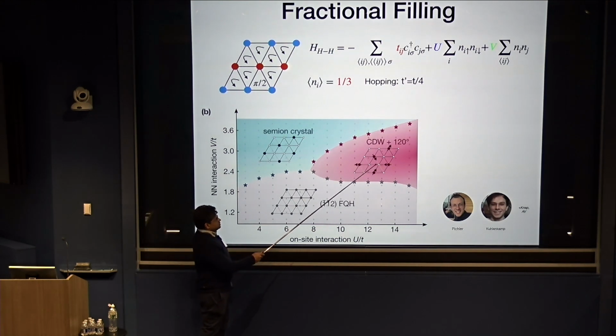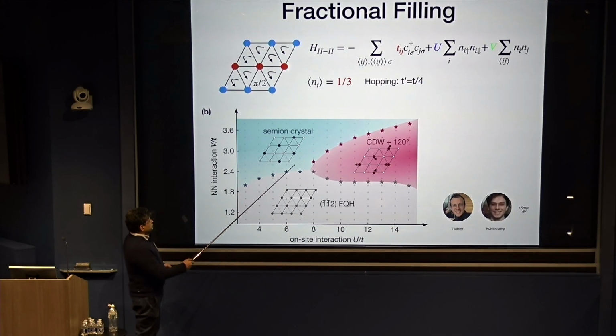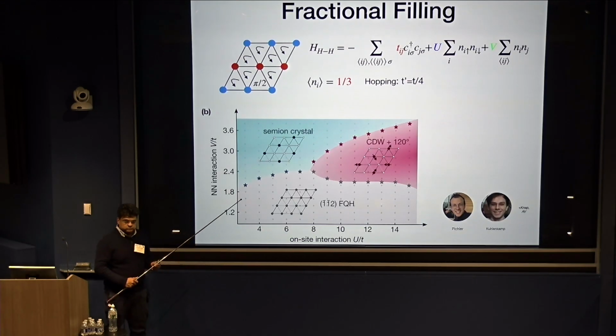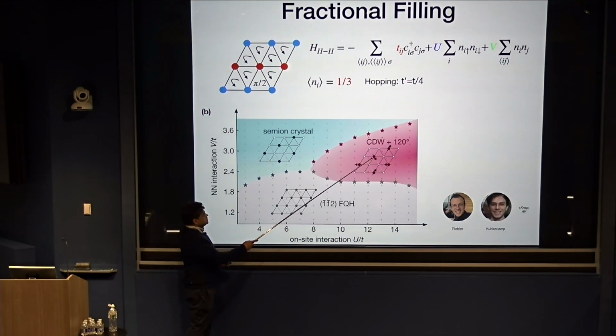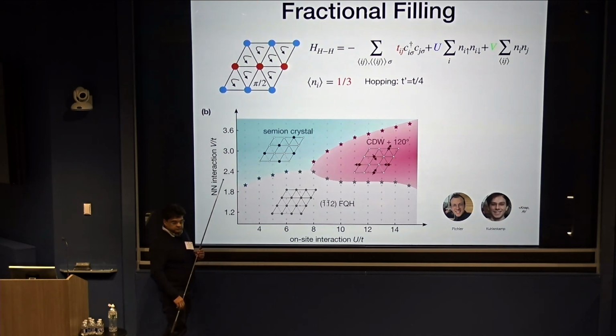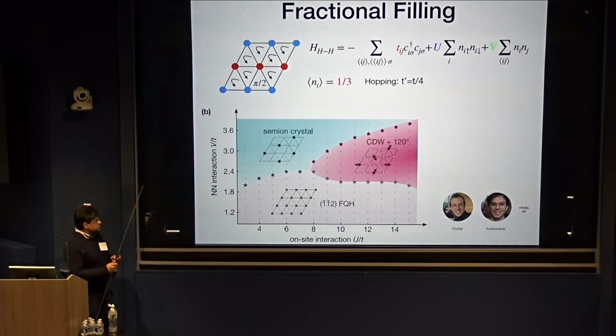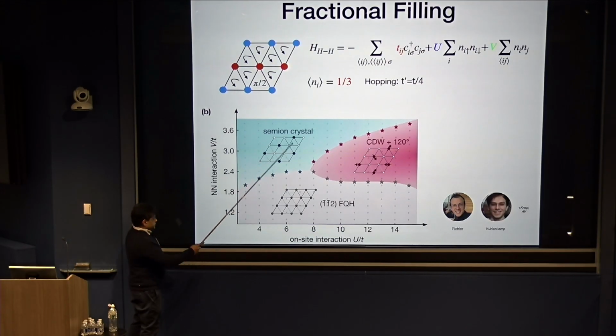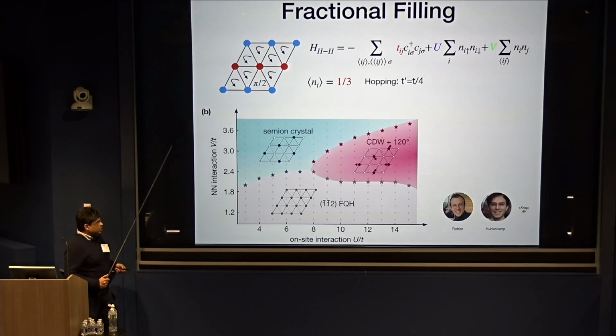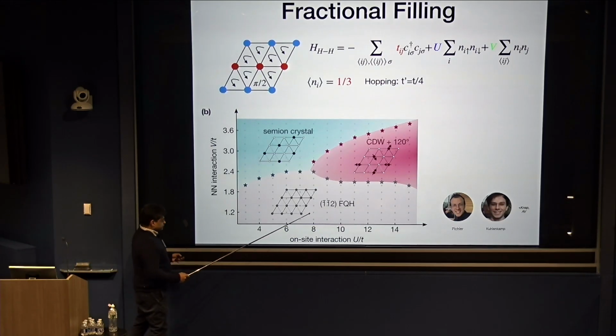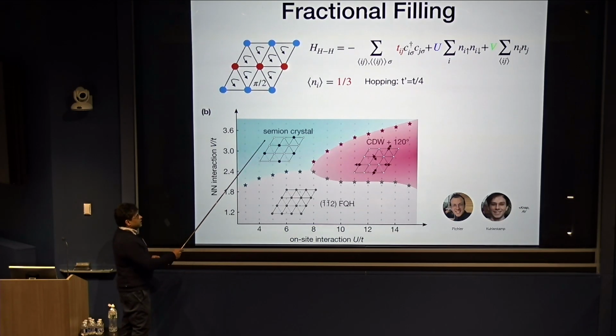One of them is a conventional charge density wave. Electrons go and form a crystal on every third lattice site. They also have spin, so that spin ends up ordering. But there's a third phase, which is very unusual, where you form, again, a charge density wave on a bigger lattice, but that charge density wave has semion topological order. So instead of having an ordered pattern of these spins, the spins disorder into a chiral spin liquid over here, to the extent that you can think of it like that. So this is a very surprising phase. It was one of the phases that Senthil and collaborators found when they were thinking about instabilities of a two-thirds phase. But in the absence of spin, it's very hard to imagine how you get this phase.